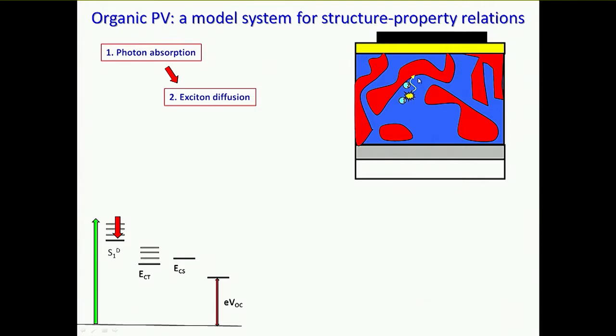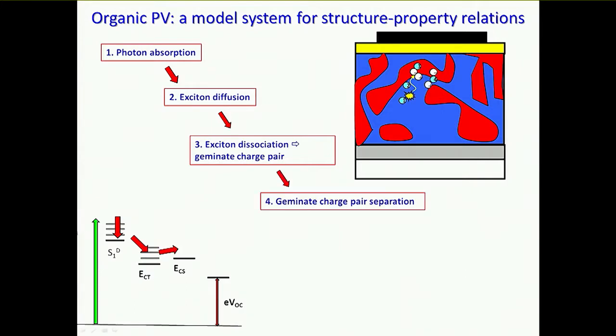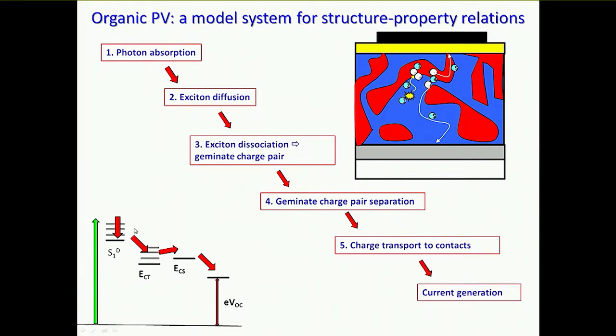And at the interface, if everything works out nicely, we may have a charge transfer event, generating some kind of semi-bound state with the charges still feeling each other's coulombic potential, but close to the interface, not yet free. They may then become free, possibly requiring energy or electric field to do that. And then once free, the charges could travel independently through the separate materials and make their way to the electrodes. And so as this goes on, we are losing electrochemical potential energy to eventually end up with the amount of work that our charges can deliver to the external circuit, and that we would measure, as if it were in open circuit, the open circuit voltage.